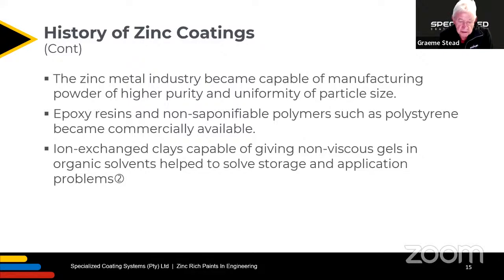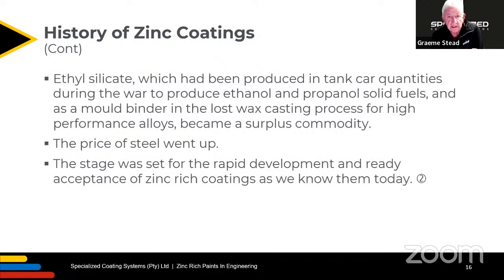Because of the high density of zinc, it sinks like a stone, and one has to keep it in suspension and supply a can that can be reconstituted by stirring in a relatively short time. And then ethyl silicate, which had been produced in tank car quantities during the war to produce ethanol and propanol solid fuels, and as a mold binder in the lost wax casting process for high performance alloys, became a surplus commodity. And in the paint industry, we are governed by the availability of raw materials.